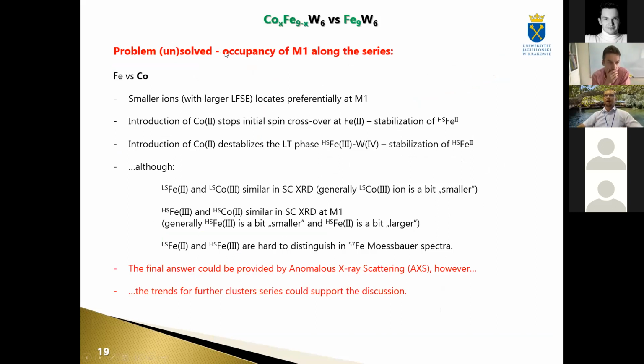Yes, because about the occupancy at the central site, we can say that cobalt could prevail over iron because smaller ions with larger ligand field stabilization energy locate preferentially at central sites. I will show it soon. Also, we noted that introduction of cobalt-2 stops initial spin crossover at iron-2 and also destabilizes the low temperature phase, which is obtained after the electron transfer. Although we still have some problem in distinguishing some of the valence and spin states by these techniques. The final answer could be provided probably by anomalous X-ray scattering. For this moment, I do not have the funds to apply for this, but maybe in future I will do this.